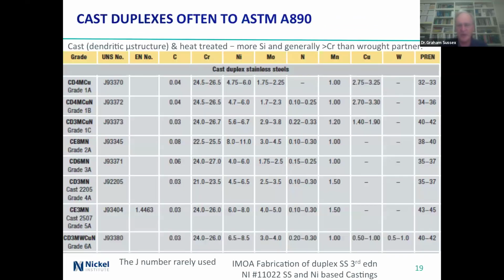And this is, I'm sorry, the only thing I've got about castings, and it's the same source. And take a look at the compositions down the side, and we've got duplex levels, we've got super duplex levels as well. The bit that doesn't show up in the top row is the silicon, because silicon tends to be just part of the actual thing. I gather we're going to deal with questions at the end. And that's basically compositions. So the J's are just not used.